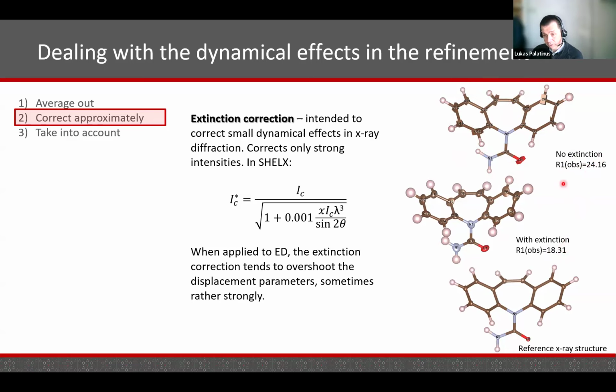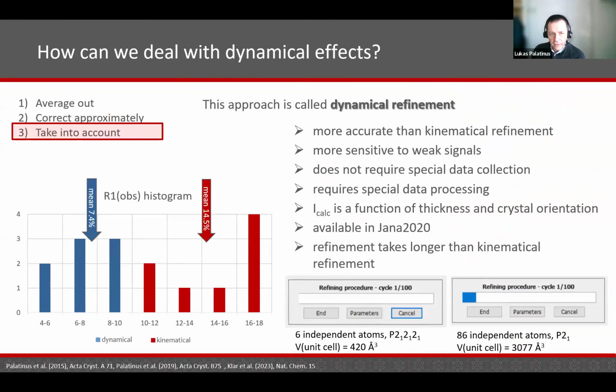But it's only an approximate correction, and the dynamical effects in electron diffraction are not weak, they are strong, and that means that the extinction correction is not really suited for this kind of dynamical effects. So sometimes it helps, but not always, and not completely. So then finally, of course, the best approach to dealing with dynamical effects is to take them into account.